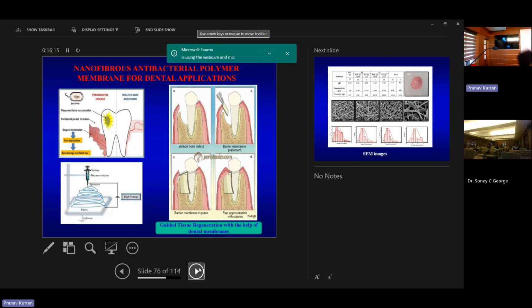So this is made using a core shell electrospinning technique, where we have tried both ways: PCL outside, gelatin inside, and gelatin outside, PCL inside. Both ways we tried. And we have added GSNO, which is called the nitric oxide complex, which has an antibacterial and wound healing property, inside the core of the core shell electrospun membrane, so that it effectively cures this dental portion.